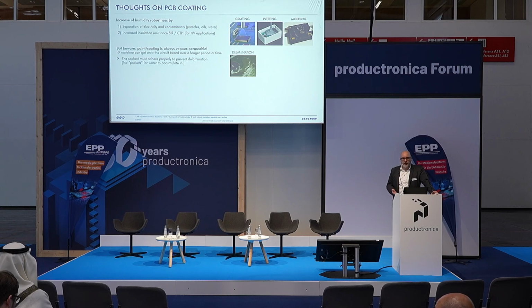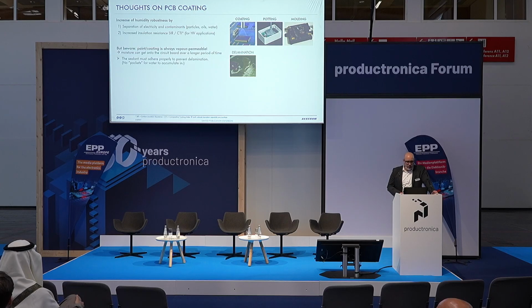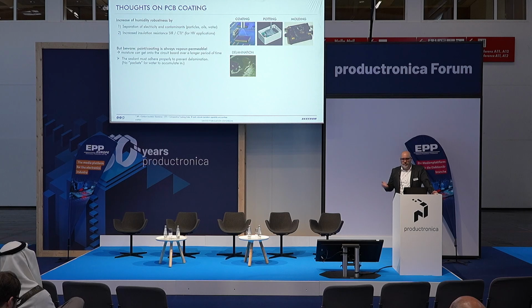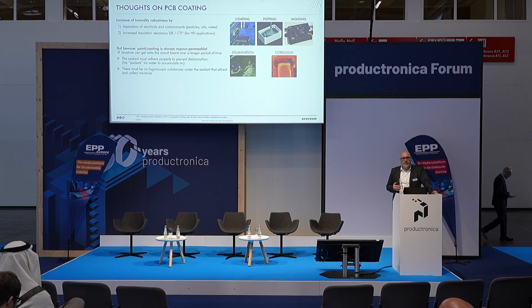So that means that your process of coating needs to be very stable and has some potential issues that can happen. So first of all, what you see here is delamination that you want to prevent. So the coating needs to really stick to your surface, so that you don't get any air pockets or bubbles below the coating where humidity can gather and build this kind of humidity pool as you saw in the video. Then you also need to avoid, together with the first point, any hygroscopic contaminations below the coating. Because if you have contamination there, for instance ionic contamination, that is actually pulling humidity through the polymer because it is hygroscopic, then the reliability and the withstand time, let's say, of the coating is reduced.